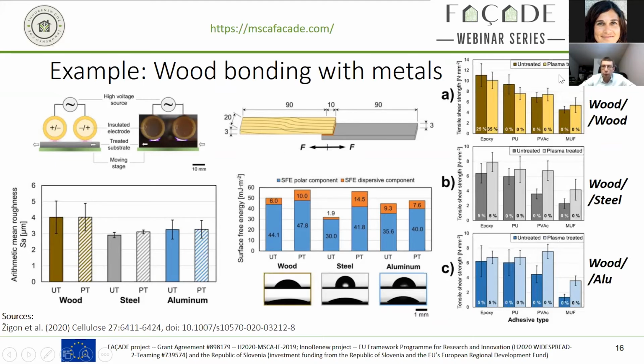For different glue systems, we have used epoxy, polyurethane, polyvinyl acetate, and melamine urea formaldehyde. For these different glue systems, there's a different impact. Particularly on wood, there's a minor increase for the typical wood glues, a minor decrease even for the less typical epoxy and PU glues. So for wood joints using these kind of adhesive systems, the plasma treatment would not be advisable. However, for the combination of different materials classes, we see an increase in all the cases.